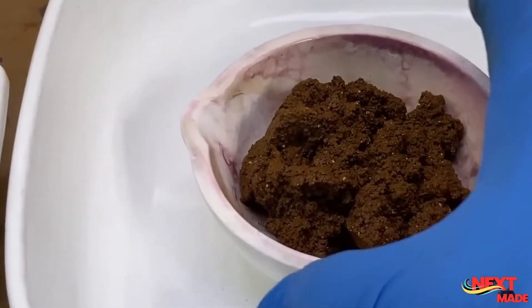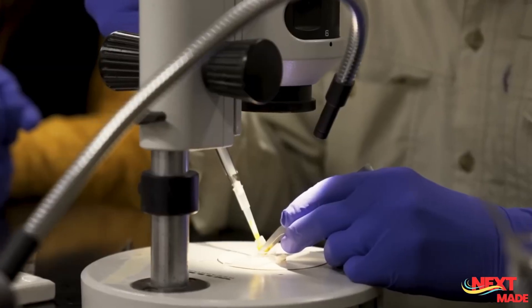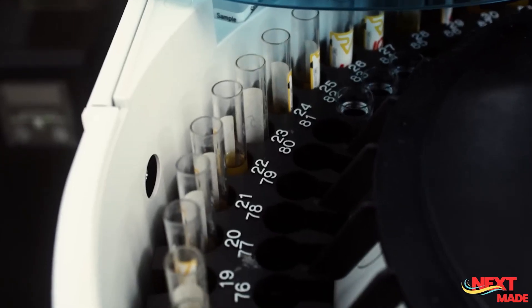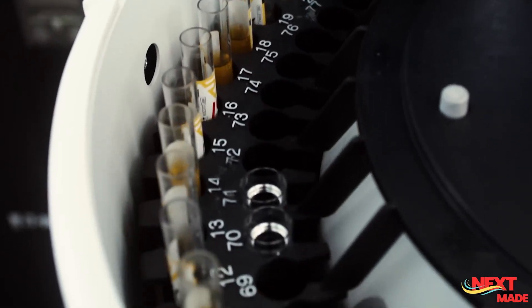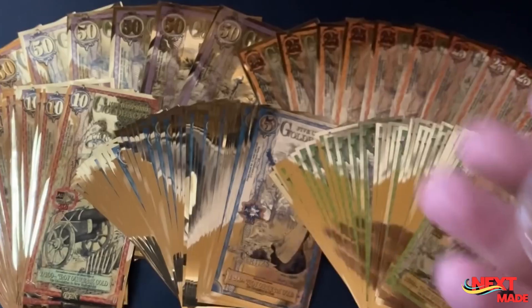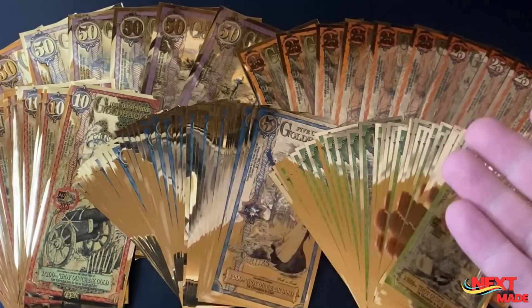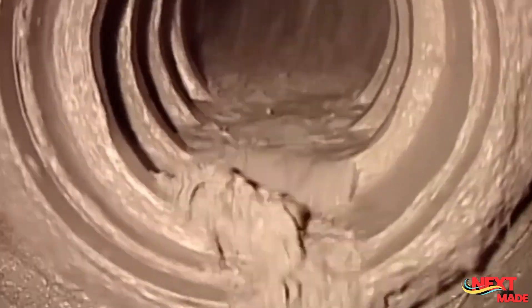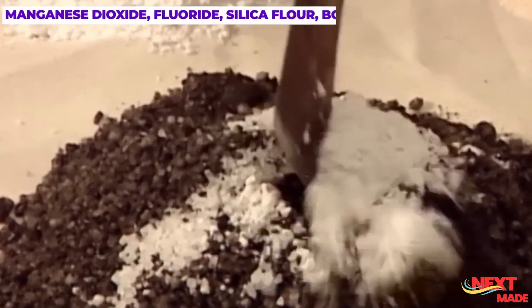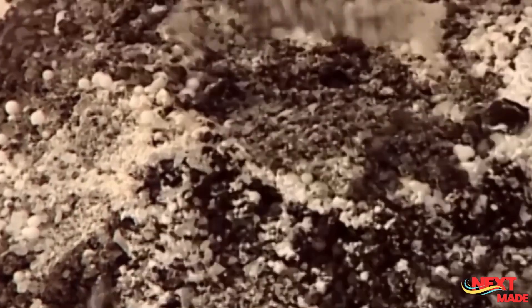The factory then adds a water and cyanide solution to the pulverized ore. Another mill grinds it further into a mud-like pulp, which flows into large settling tanks. The wet solids, being heavier, sink to the bottom and the water at the top drains to another area. Workers transfer the wet solids into an agitation tank and blow in air. This process, called aeration or air agitation, introduces oxygen into the slurry.